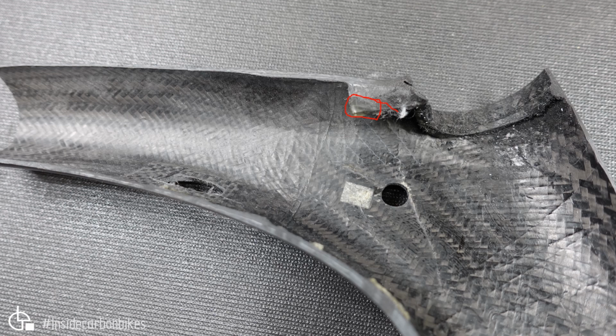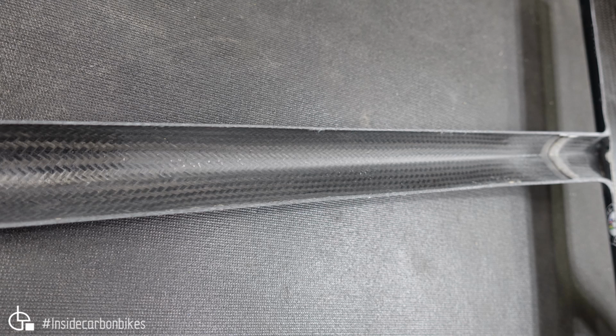So that's not ideal, but it's not a deal breaker either, so there's not that much of a problem. The resin obviously has much less mechanical properties than the fiber, typically about 1% of the strength and stiffness. So you're going to lose a little bit, but that area will be significantly stiff anyway. There'll be no issue with stiffness through that section. Looking along the top tube, again, nothing of note here. It's all very uniform.